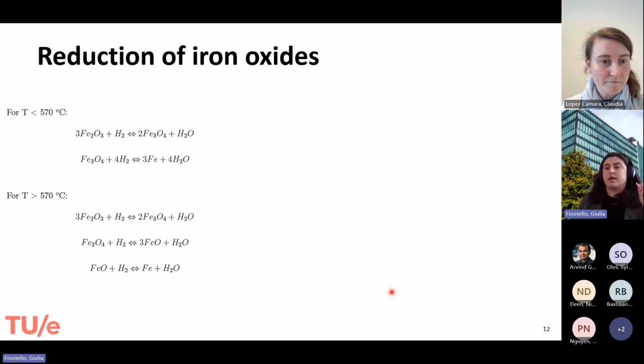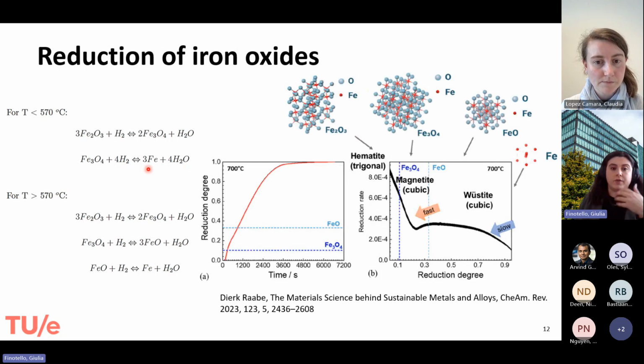If we look into the reaction, we have different reaction steps. Below 570 degrees, we have what we call two-step reduction, and above we have three-step reduction, and this is because wüstite is stable only above 570 degrees. Below that we don't form any wüstite. So by literature, if we look at the reduction degree, in this case we have 700 degrees of reduction temperature. So we are above 570, which means that we are forming wüstite. In this case, my reduction proceeds over time, and I'm able to reach 100% conversion after a certain time.